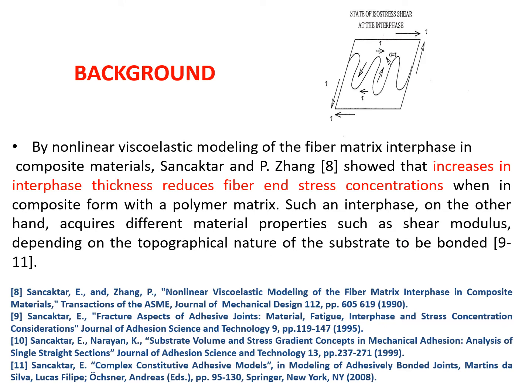We also performed nonlinear viscoelastic modeling by using numerical analysis of the fiber matrix interphase in composite materials. We showed that increases in interphase thickness reduces fiber end stress concentrations when in composite form with a polymer matrix. We also showed that the interphase modulus also affects the stress state, with typically softer interphases acting to reduce the stress concentrations.